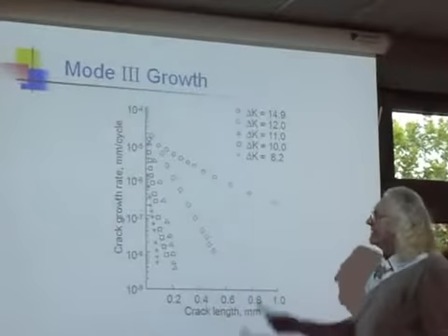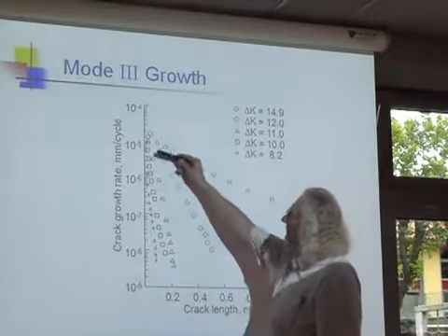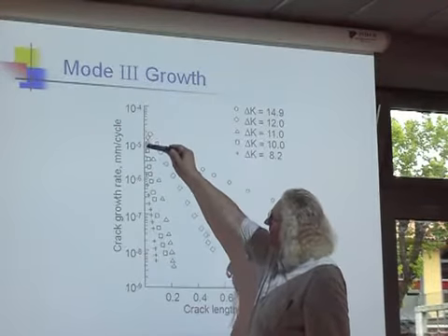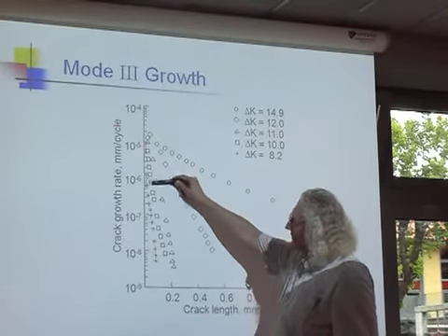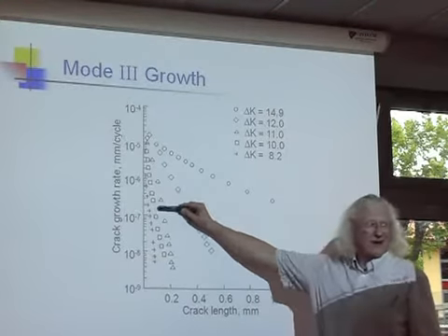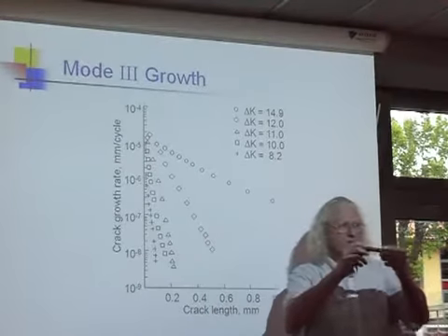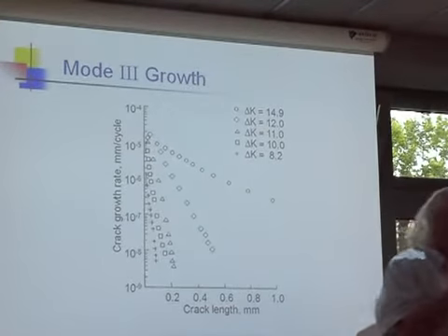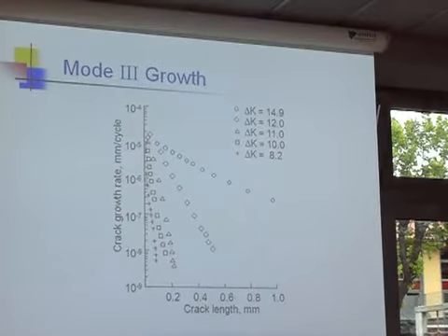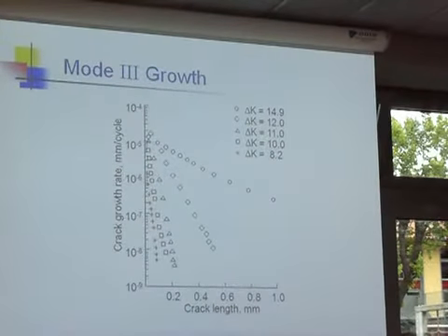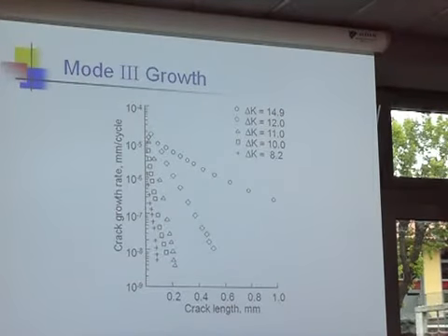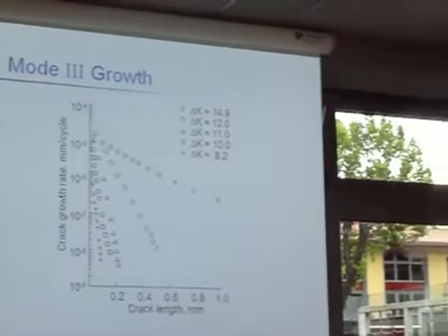And then, let's just look up here. Delta K of 10. Just make it smaller. Okay, it starts off, and the growth rate is here, a little bit slower, but look. 1 order of magnitude, 2 orders of magnitude, 3 orders of magnitude, just because of building up these friction forces. So most of the mechanics models are useless, because they don't get the primary rate. And how do you calculate the friction? No one knows. There are no good friction models. It's a very, very interesting and important research area.